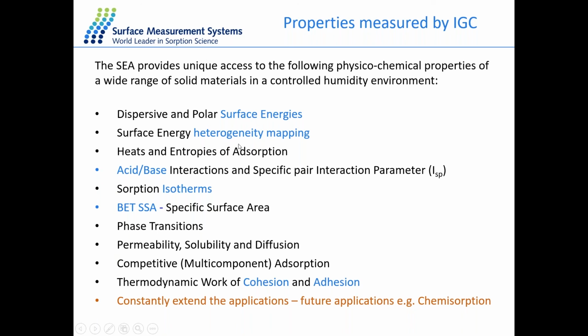And from the surface energy, we can also calculate the work of cohesion and adhesion. And the balance between work of cohesion and adhesion is a very good parameter or indicator for the formulation study of the multiple component systems. And some other property we can also measure with IGC. For example, we can get the Ka, Kb value from the acid-base interaction on the surface, as well as we can measure the phase transition for the glass transition temperature, or the Hansen solubility parameter with a series of different solvents interact with the solid material.